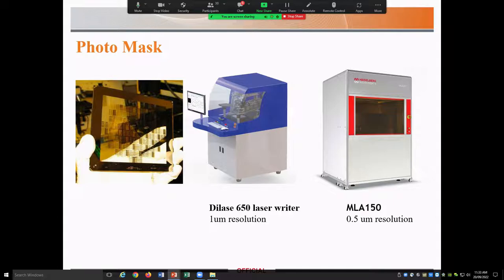Basically, we've got the glass or quartz plate, and then it is coated with chromium. Photoresist goes on top, and then an electron beam or precise lasers are used to transfer the design onto the surface of this photoresist. Then the unwanted parts will be removed, and chromium will be etched off from the open areas. And then when we wash off the photoresist from the surface, we will have a plate with chromium patterns on one side of it. It is quite important when we are making a mask that we choose the right polarity in our mask design.